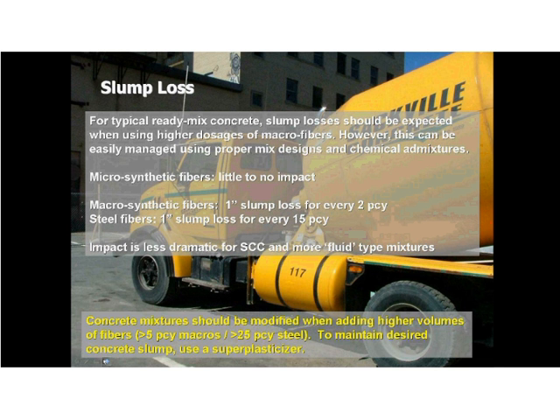As a contractor, when you see slump loss, your first indication is typically to put more plasticizer, more water reducer, or water if it's necessary. However, water should not be used when using fiber reinforced concrete because that will alter other properties, including possibly lowering the strength. As another general rule of thumb, when a concrete producer is supplying macrosynthetic fibers, you can expect an inch of slump possibly for every 2 pounds of fiber or for every 15 pounds of steel fibers.